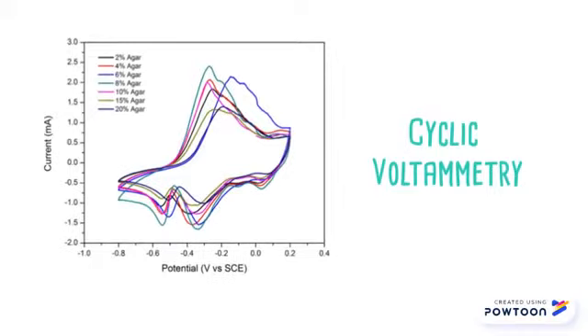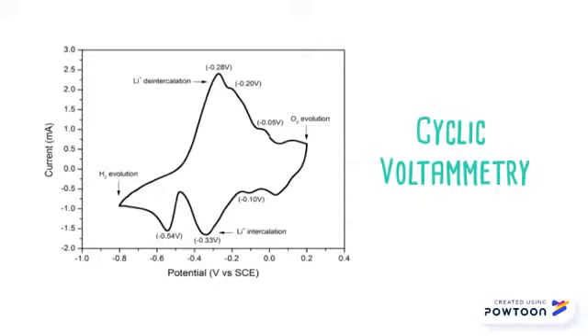Cyclic voltammetry analysis will be carried out first. From the CV curve, we can see that 8% Agar has the most prominent curve and it has the fastest reactions among all. For the 8% Agar electrode, 3 pairs of redox peaks were observed for the LVO working electrode. This is due to the intercalation and deintercalation of Li ion into and from the layers of the LVO structure.